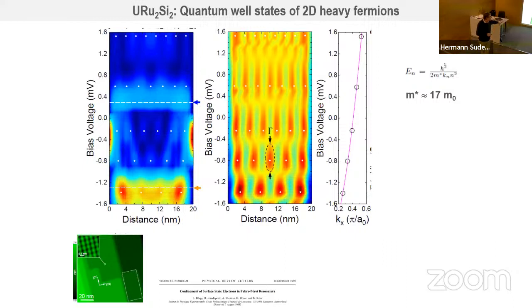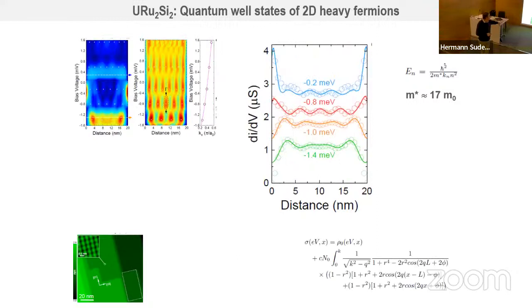And so you see that the levels are kind of quantized, and you see that they increase with energy. So we did not catch the bottom of the band, which is hidden here, and something else happens there. But essentially, the important thing is that this effective mass is actually very high. And you can make scans of the conductance, and you can follow this quantization quite nicely and fit using a Fabry-Perot arrangement.